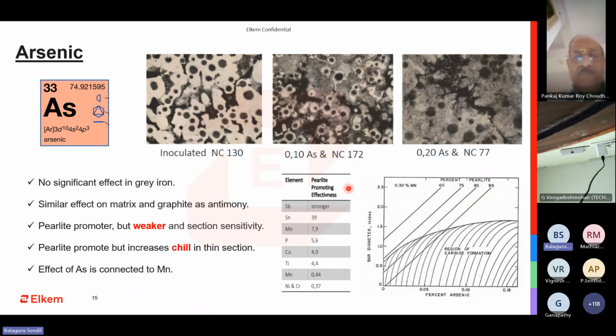The effect of arsenic is also connected to manganese. So this chart I have put here. You can see that it promotes carbide in this particular range when you are operating from 0 to 0.15%, and you are having a round bar diameter of about 1 inch, 25 mm. Once you have much thinner sections, less than 25 mm, about 12.5 mm, then the percentage of pearlite will be high. At the same time, you also get into a region of carbides.